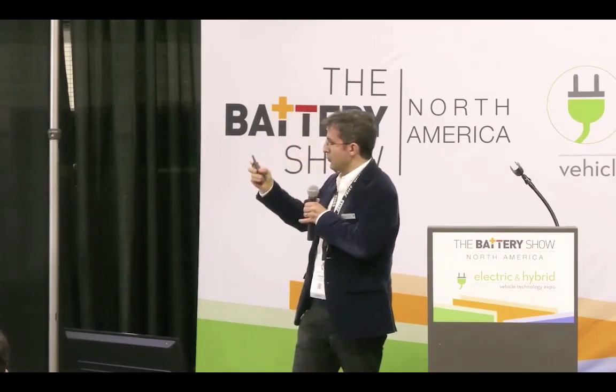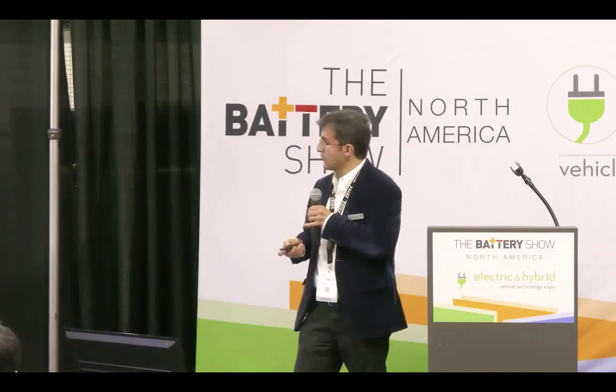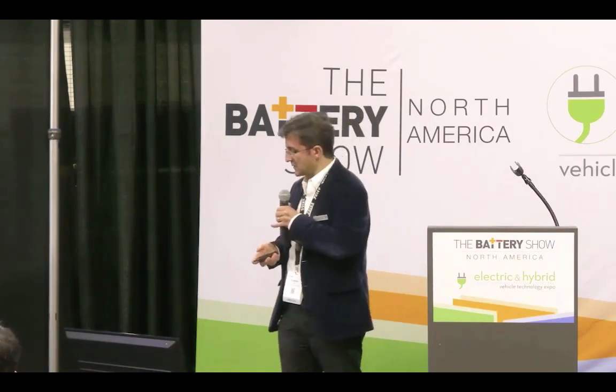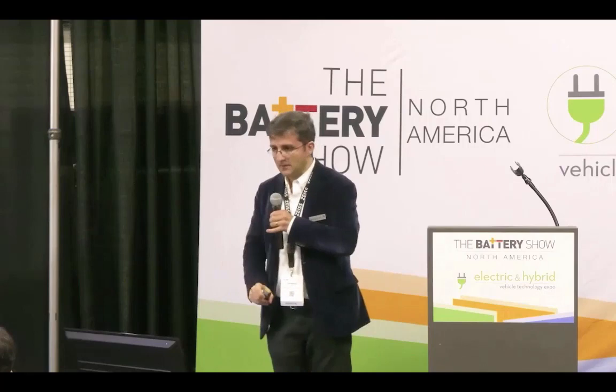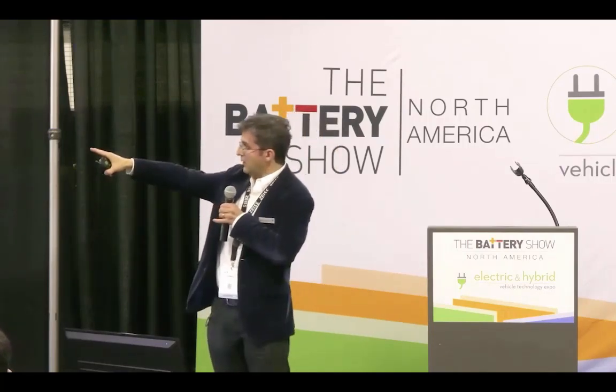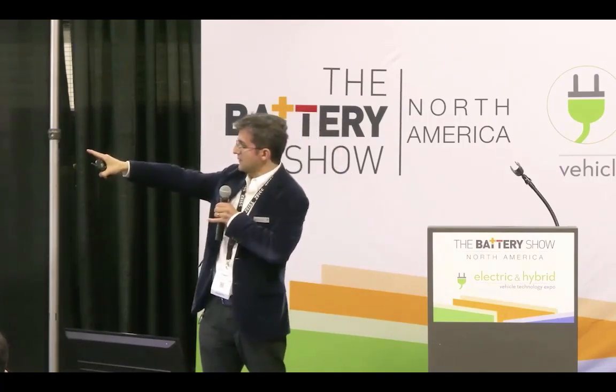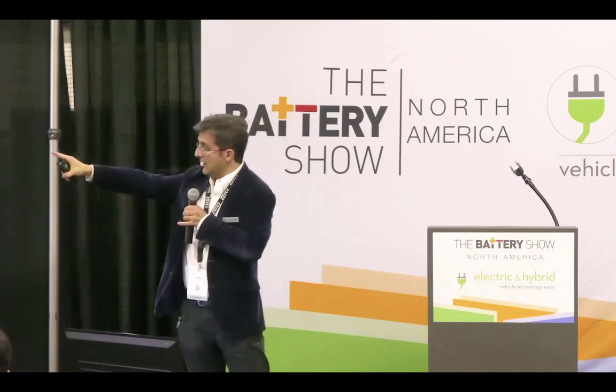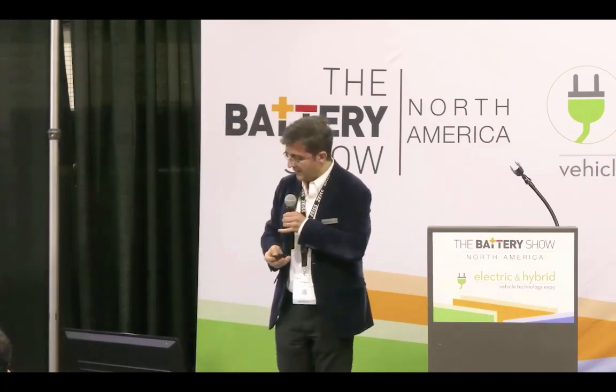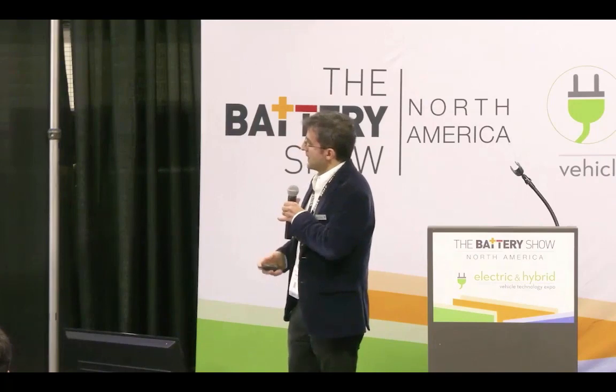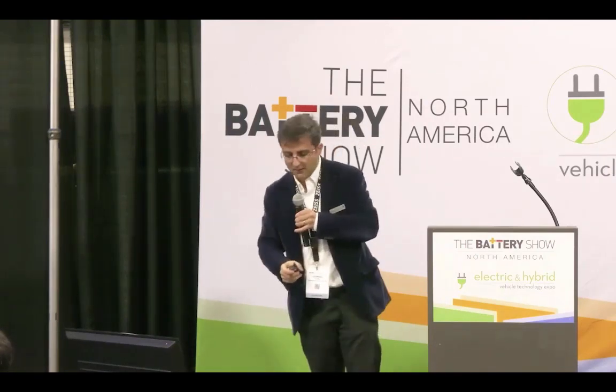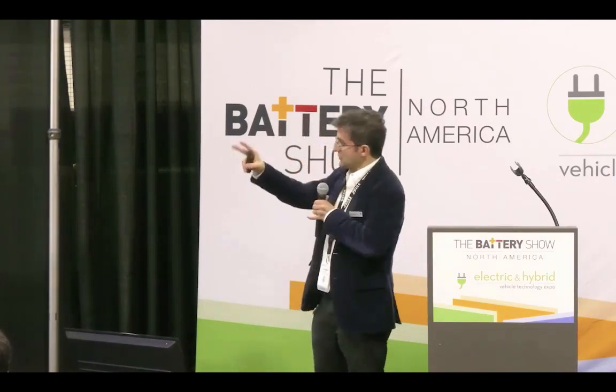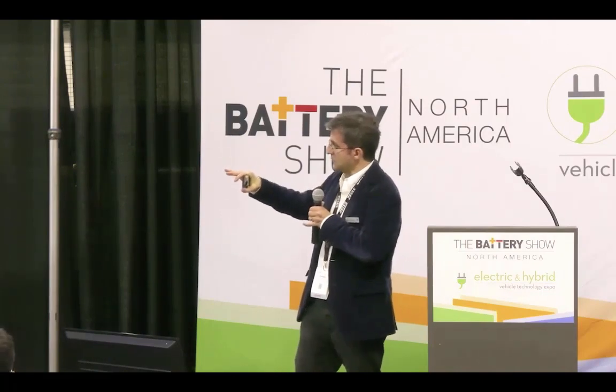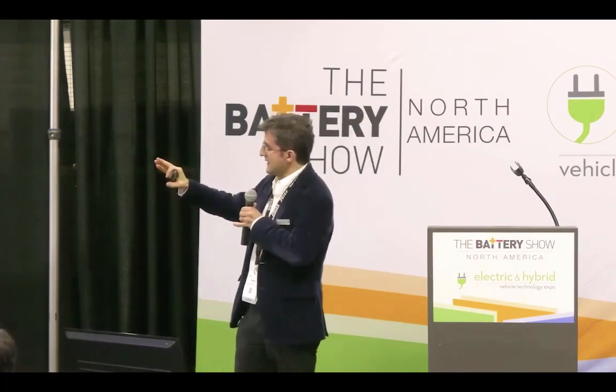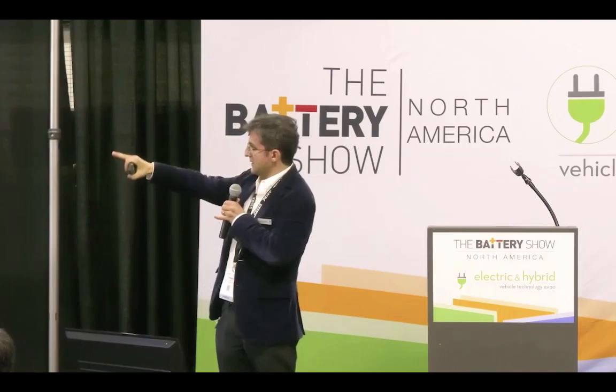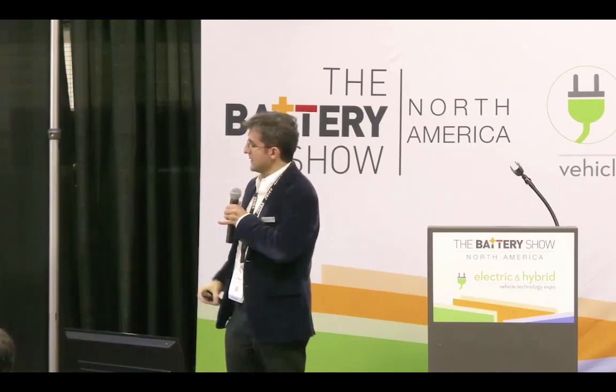And we wondered what happened in the process. So we decided to scan the battery also at 100 cycles, and we can detect how the silicon is being consumed and is generating those cracks and porosity. And this is a scan of the portion of the battery at a higher resolution where that crack was. And you can see how there is the destruction of the particles there.